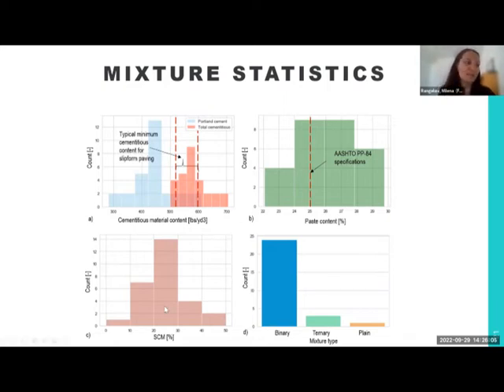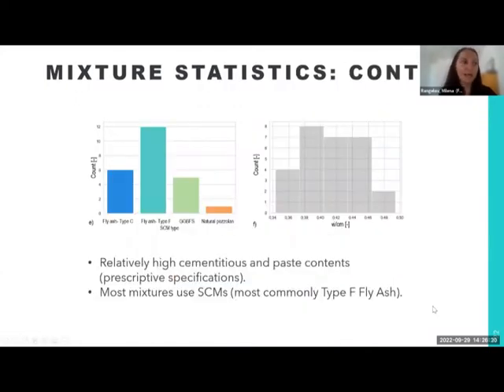In terms of SCM usage, pretty much most mixes are using some SCMs, and most common replacement ratios are between 20 and 30%. There was only one mix without SCMs, and that is the Hawaii mix. They don't have SCMs available. Most mixes are binary, meaning they use cement and one type of SCM. We also have some ternary, and again, one plain mix from Hawaii. In terms of different SCM types, most mixes are using type F fly ash, some are using type C as well as slag. In one mix, I believe it was Nevada, they used natural pozzolan because that was locally available.